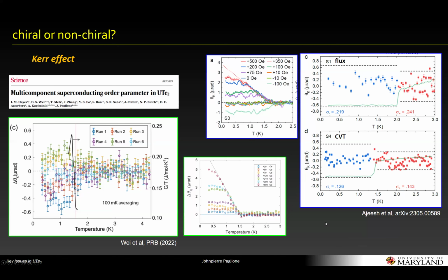Question? Do you know whether the Los Alamos group did the Kerr rotation on the original samples, the CVT samples? Did they see a signal there? Yeah, this is the experiment here, and I don't see a signal there. As I said, they claim not to see any spontaneous Kerr effect in both types of crystals. Now, granted, these are their crystals, and what Priscilla tells me is that they have trouble making crystals with this technique that show a double transition. I promised to send her some samples so they could reproduce it, so we have to do that. But you can see the TC here is 1.5K or so. So I think they just need to do more measurements.